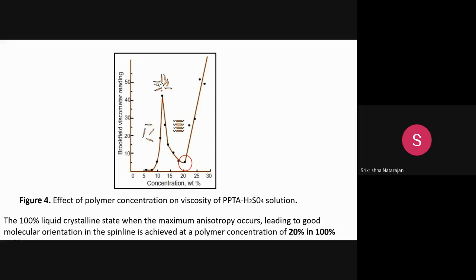You can see here uniformly the nematic crystals which are shown here, it is oriented. So because of this, it produces the fiber with a good molecular orientation, and that happens only at a particular viscosity. Okay, so for this reason we dissolve this. Normally we take around 20% polymer and dissolve it in the 100% sulfuric acid, so that we get the liquid crystalline state. At this state only the maximum anisotropy occurs, that is, different properties in different directions, so that you get the fiber with good mechanical properties, the higher strength, the higher modulus.